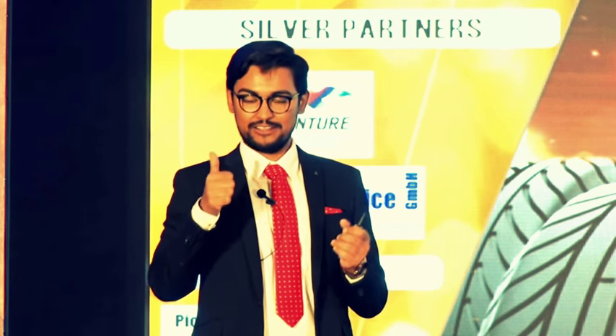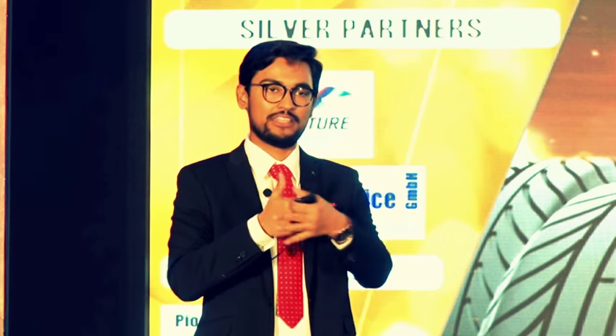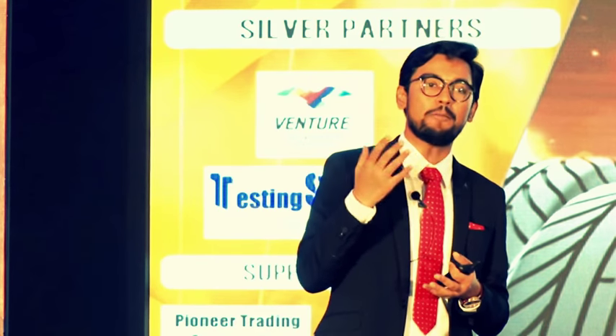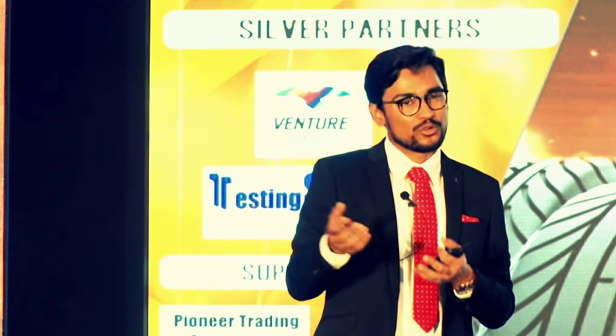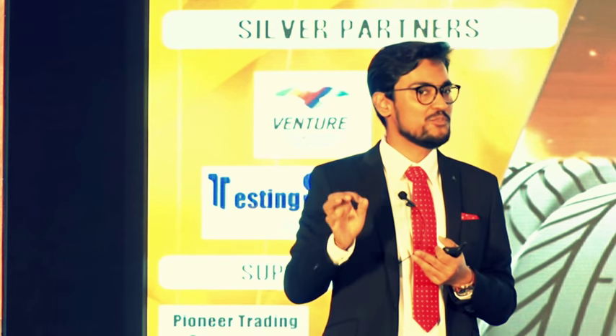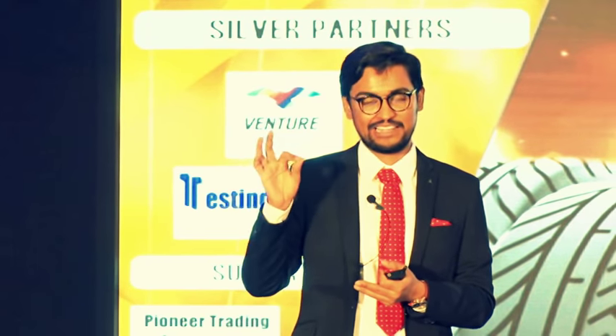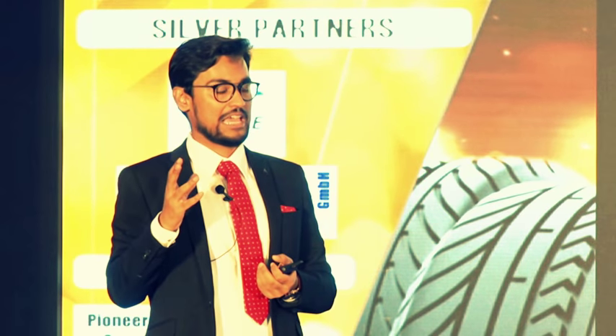Okay. In NR and NBR, this is not a very commonly faced phenomenon by us. If it is a low viscosity polymer, it is a commonly faced phenomenon. The reason I think would be the same for NR or any other polymer. The surface energy of single-walled carbon nanotube is extremely high, so it would tend to get a phase separation until you blend it to that level that it binds in the polymer chain. Then that phase separation doesn't happen.